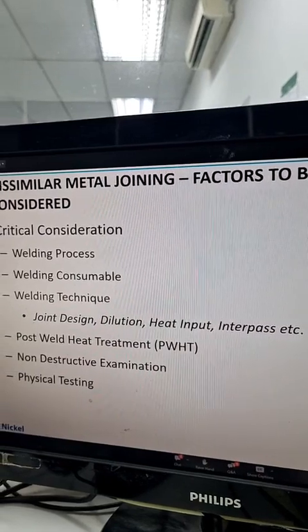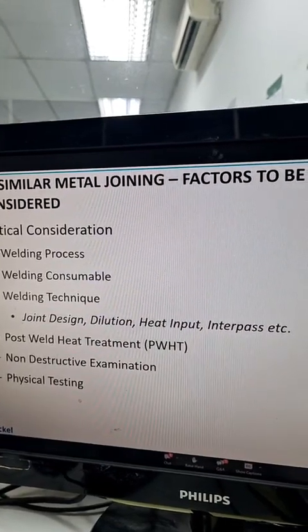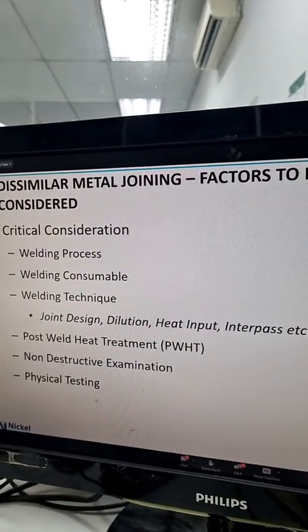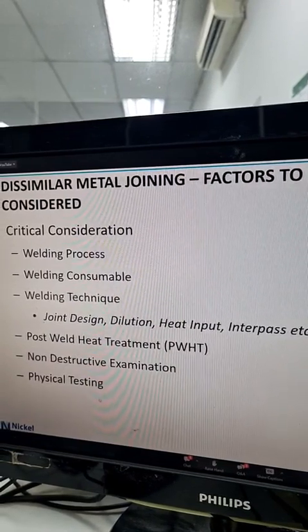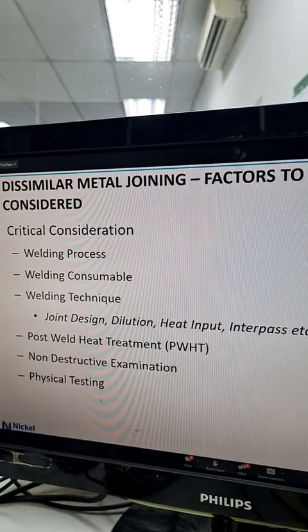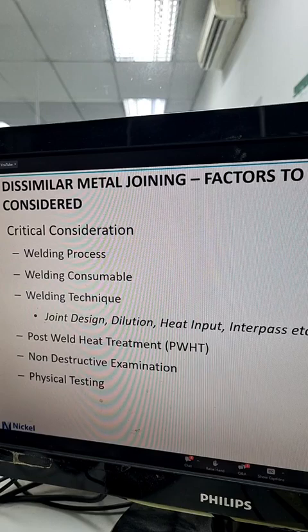As we are getting into the conclusion part, you need to take care of the critical aspects like the welding process, welding consumable, the welding technique, within the welding technique, joint design, dilution, heat input, the interpass, what PWHT you are subjecting it to, what NDT you are planning to do on the joint, and what physical testing you are subjecting it to during your procedure qualification.